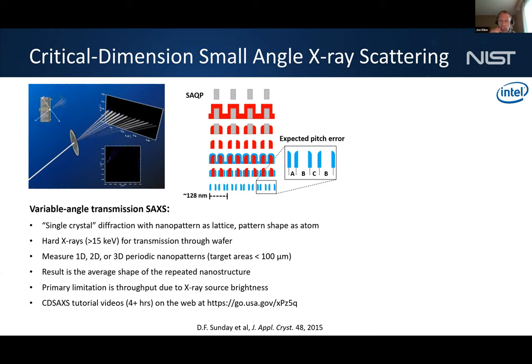And one of the big challenges that they had with this is if you don't have the width of all three of your layers exactly tuned right, you can end up having a pitch error in there, because they really want to have it look like you directly deposited or directly patterned it to the right pitch. And so they have a number of different things they have to adjust to be able to keep that right.